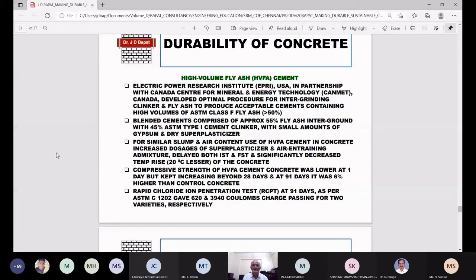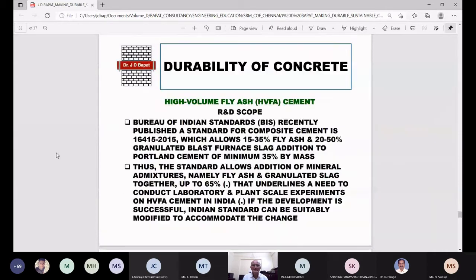Now, what is the R&D scope in this? Maybe important for people who are doing R&D in concrete. Bureau of Indian Standards (BIS) recently published a standard for composite cement, that is IS 16415:2015, a very recent standard, which allows 15 to 35% of fly ash and 20 to 50% of granulated blast furnace slag addition to Portland cement of minimum 35% by mass. So the standard allows addition of mineral admixtures, namely fly ash plus granulated slag together, up to 65%. We are already allowed in Indian standard.